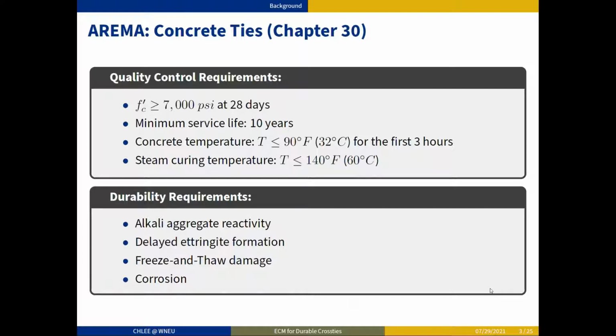The American Railway Engineering and Maintenance of Way Association, which is AREMA, provided several guidelines. First of all, the strength should be greater than 7,000 psi at 28 days, and the minimum service life of the cross ties should be 10 years. Also, there were several quality control requirements related to the concrete and steam curing temperatures.